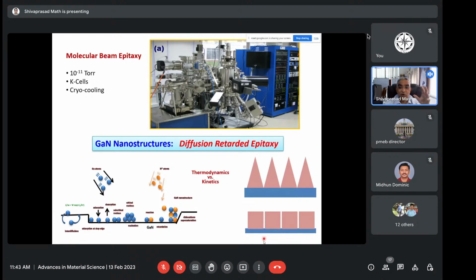Whenever I grow gallium nitride on a sapphire substrate, there's a lattice mismatch of about 16%, which makes dislocations in the material. You have two kinds of dislocations. If the lattices shift this way, we get an edge dislocation, and if they shift like this, we call it a screw dislocation. These dislocations carry through the material and create a lot of defects. This has been one of the major limitations in the efficiency of gallium nitride based LEDs.